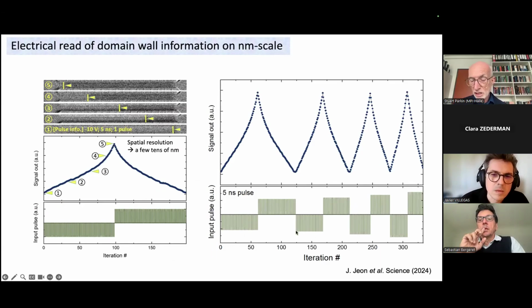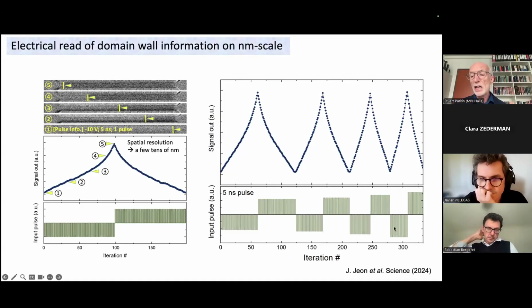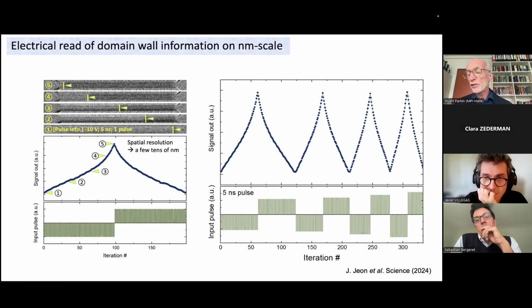And then we increase the intensity of the current pulse so that we need a smaller number of current pulses to take the domain wall from one end of the racetrack to the other. And so as you progress, with these numbers of iterations, we're increasing the intensity of the current pulse for the same current pulse width, and you can see that the domain wall is moving faster, so we need smaller numbers of current pulses to take it from one end to the next.